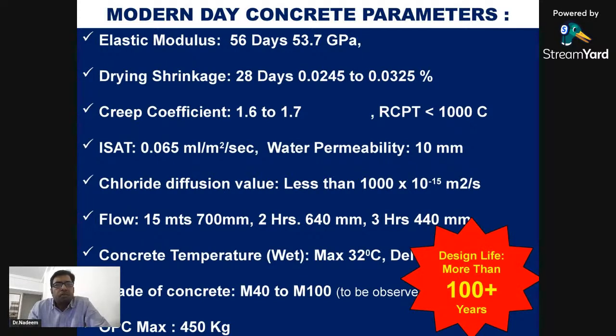Elastic modulus at 56 days in the range of, say, 54 GPa (gigapascal), drying shrinkage at 28 days less than 0.025, or in the range of 0.025 to 0.0325, creep coefficient as low as possible in the range of 1.6 to 1.7, RCPT (rapid chloride penetration) less than 1000 coulomb, ISAT (initial surface absorption test). Again, the requirement from the durability perspective is 0.065.